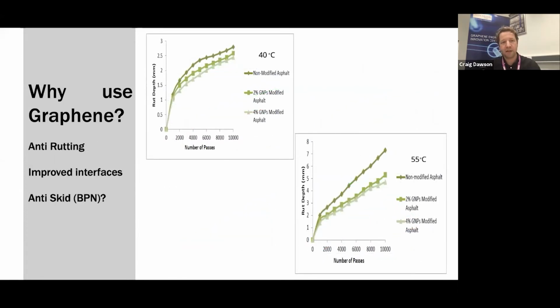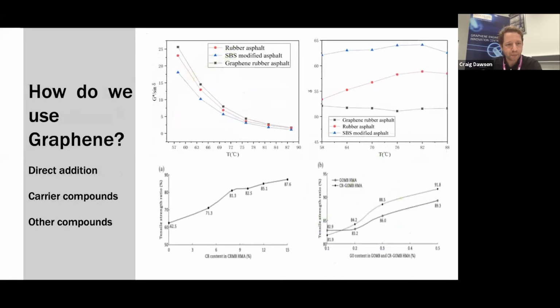Anti-rutting effects. We see improved interface between, these are academic claims, improved interface between the aggregate and the bitumen, and in some cases they're even claiming anti-skid properties. But I'm not entirely convinced of that at this stage. Not that we've tested it. I think it's a dispersion issue and a texturizing issue that they claim is there, and I'm not sure it would be there if you use the graphene more effectively.